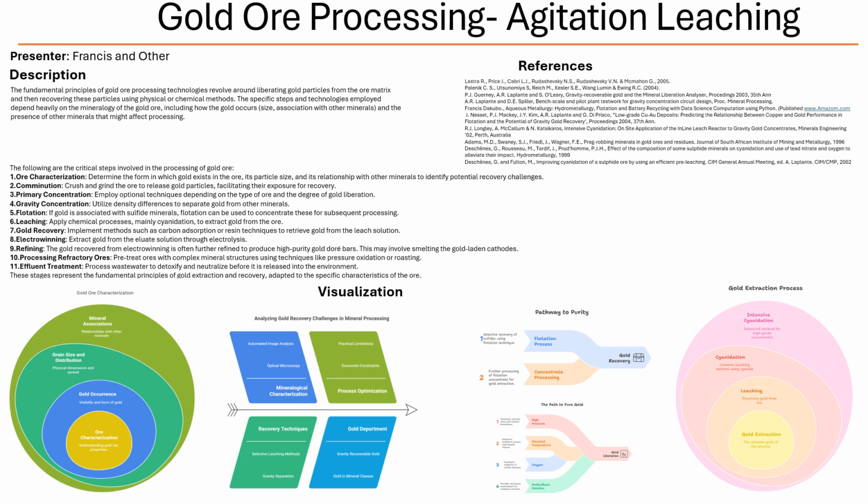If you grind the ore too finely, you can actually reduce the amount of gold that's recoverable by gravity. Wait, what? How does that work? Well, think about it. If you grind the gold down to really tiny particles, they might not have enough mass to settle out effectively, even under gravity. They might just get carried away with the lighter minerals. Huh, so there's like a Goldilocks zone for grinding. Not too coarse, not too fine. Precisely. And that's where computer simulations come in. They can help predict how much gold will be recoverable by gravity at different grind sizes.